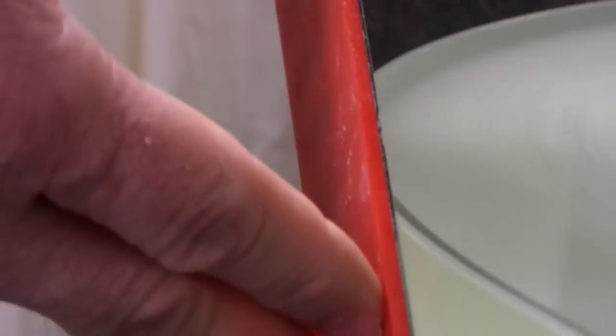You like it to be against the mirror turning away from you and not into you. But just to show you a little bit what it looks like, I'll do it from this side. And the trick is you want a little bit of movement on the hone because it has this pattern where it's missing diamonds there. So you need to move it a little bit or else you'll leave little lines on the edge of the mirror. But it only takes a few minutes to clean the edge of your mirror like this and keep it clean during the course of grinding and polishing.